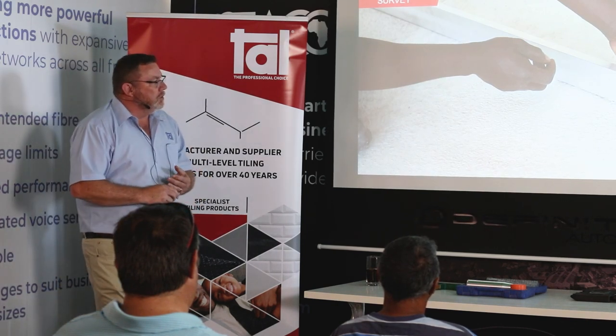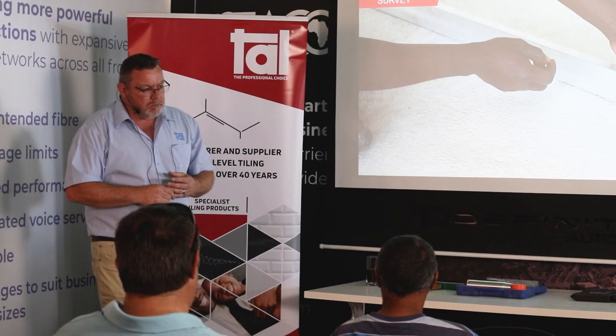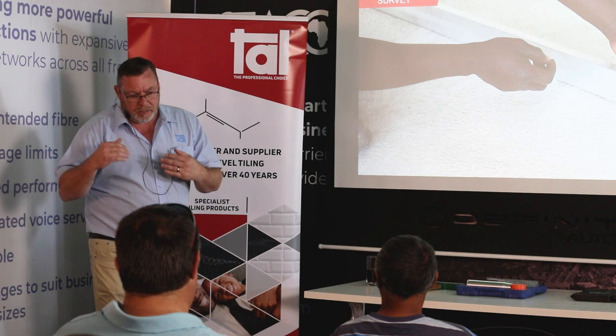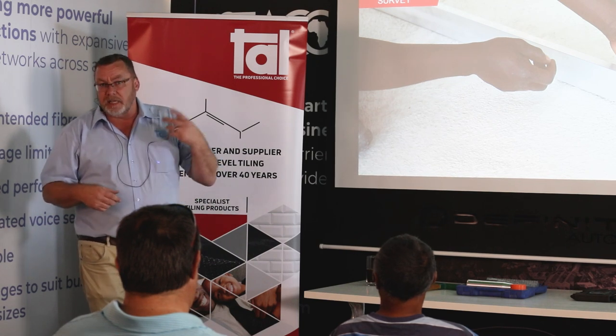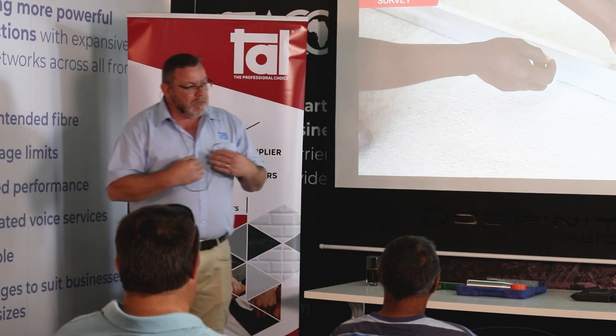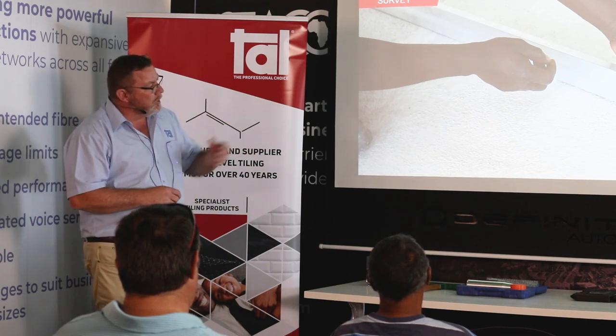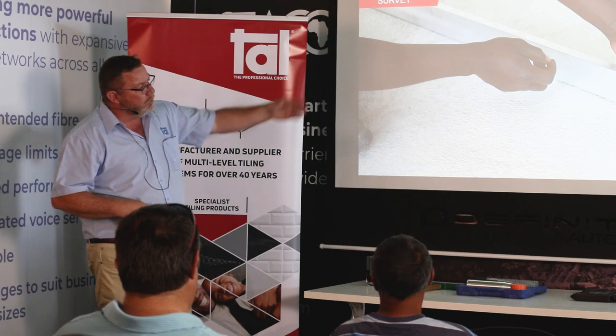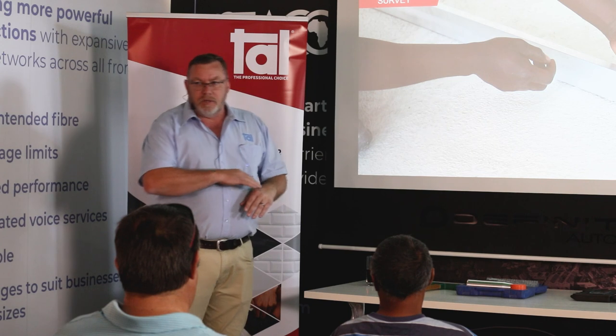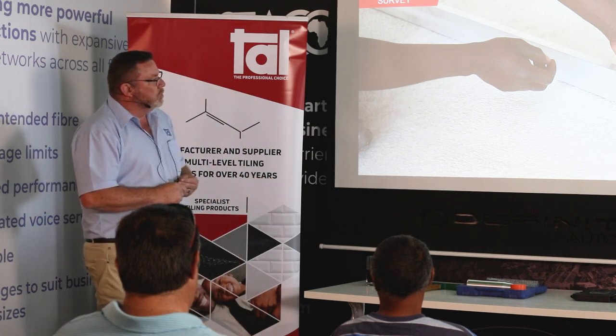Before you put your primers and self-levelings on the floor — and I speak largely towards vinyl because we sell a lot of screeds into medical facilities, hospitals with sheet vinyl, and residential and commercial environments with LVT — it's important that the contractor understands what they're dealing with. They should be putting a straight edge on the floor before they start to ensure they fill any low areas first. If you put a self-leveling screed onto a floor, it will smooth up but it follows the contour of the floor. So it's important to do your due diligence and check whether you've got highs and lows.